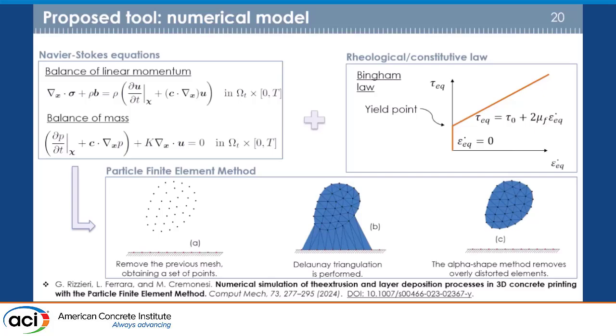We are now going to implement rigid viscoplastic, and also elastoviscoplasticity, into that. It's based on the particle finite element model. You see there we start from a set of points and we generate a mesh through the Delaunay triangulation process. After that, we have to implement some element distortion control technique, which does not only take out the elements which at the beginning of the problem modeling are too distorted, but also helps us keep the computational time reasonable by removing elements which become too distorted in the process of deformation.